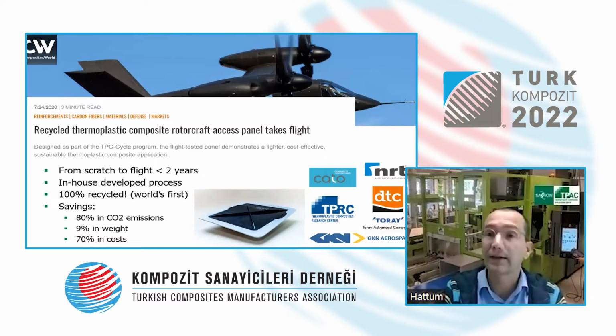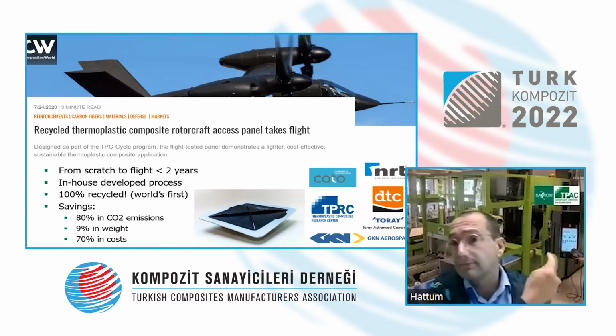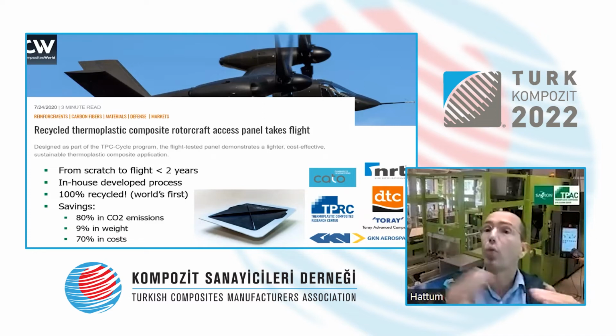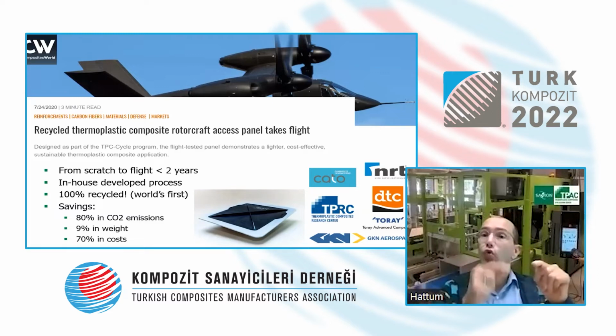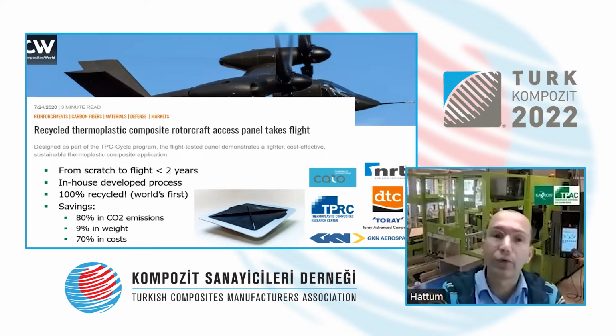virgin material part. And also because we reduced the processing time from, well, you can see our machine, from 1.5 hours in autoclave, out of autoclave, to minutes, we reduced the total panel cost by 70%. So the current production is only roughly a third of the cost of the original production.